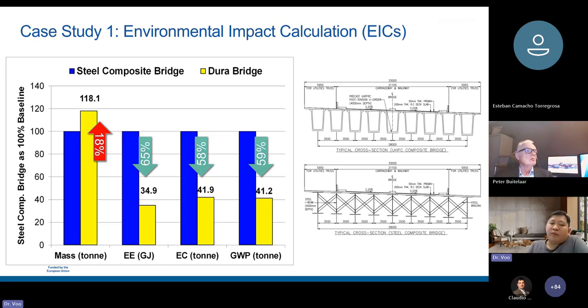So what this diagram shows is that the UHPC superstructure is about 18% heavier compared to the steel composite bridge. But the embodied energy is about 65% lower, the embodied carbon is about 58% lower, and the 100 years global warming potential is about 59% lower.